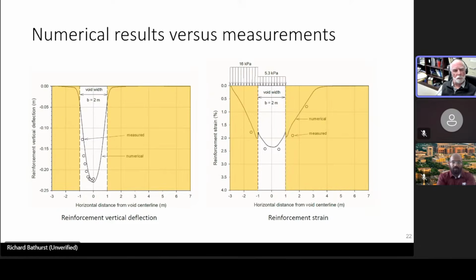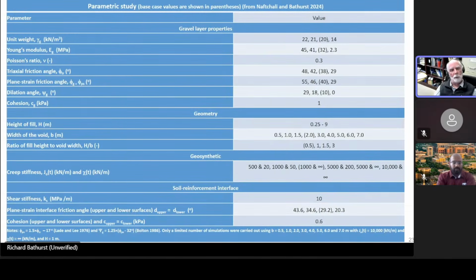So with confidence in this model, we carried out a parametric study, and we varied the input parameters to this problem. This is including the geometry and the properties of the materials. You can see we used a range of unit weights, friction angles, and cohesion for the fill soil. We looked at a range of geometries with respect to height and width of the void. This gave us a range of height to void width ratios. And then, of course, we looked at the effect of the reinforcement stiffness parameters that you can see here.